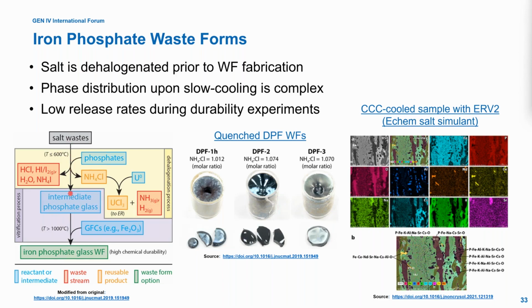So the intermediate that comes from this initial reaction at 600 degrees C is an intermediate phosphate glass that's not chemically durable. So it's reacted with glass-forming chemicals like ferric oxide and vitrified at high temperatures, up to say 1,000 to 1,200 degrees C, to create a chemically durable iron phosphate glass waste form that can have different iron phosphate crystals in it as well.